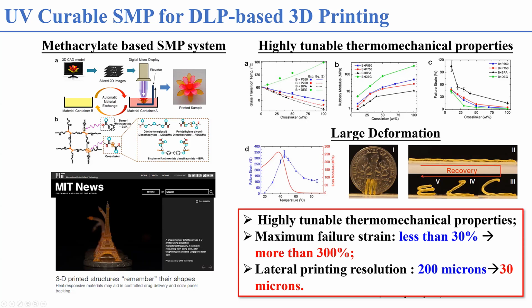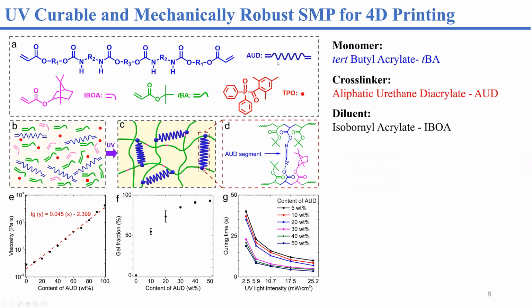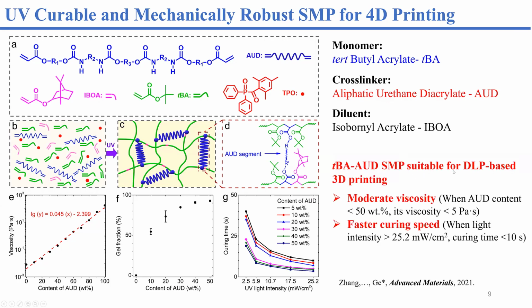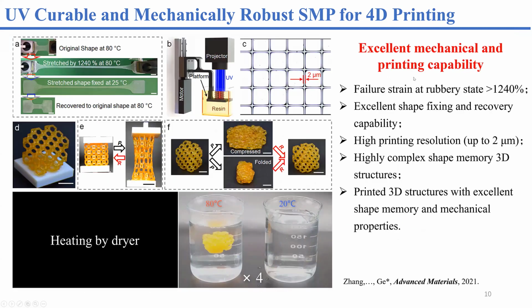So we also developed a new material system, a UV curable and mechanically robust shape memory polymer for 4D printing. The monomer is just tert-butyl acrylate, and we use a special cross-linker called aliphatic urethane diacrylate. This material system shows good suitability for DLP-based 3D printing, with a moderate viscosity and a fast curing speed, much faster than the methacrylate-based shape memory polymer. More importantly, it exhibits excellent mechanical and printing capability.